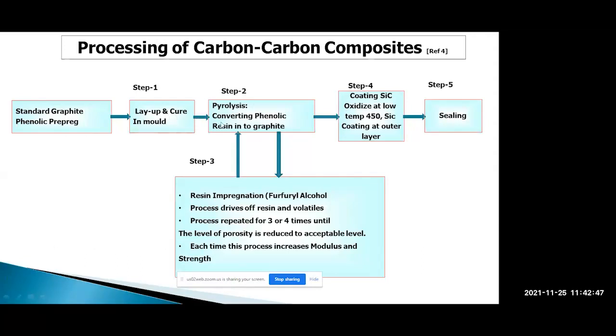Pyrolysis means converting phenolic resin into graphite. Then step 3 is the resin impregnation. So that is this porous structure. This will result in a porous structure. In this porous structure, we have to infiltrate and impregnate the resin, and this process has to be done 3 to 4 times to reduce the porosity and slightly increase the density.